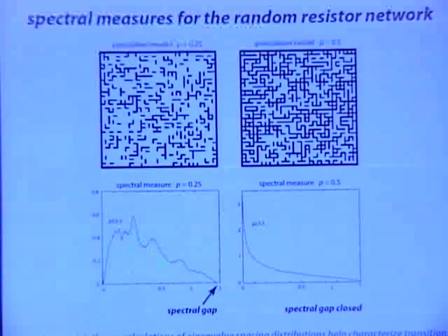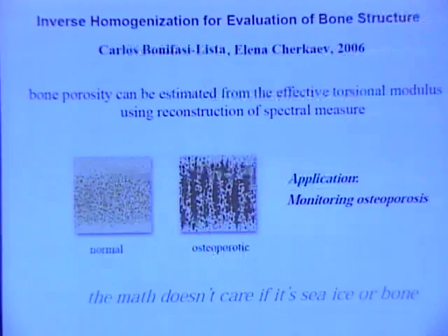The area under this curve here represents the probability, 25%, the probability of finding one of these bonds, and the spectral gap indicates that it's disconnected, and that spectral gap disappears as the system becomes connected. And there's a lot of what's called random matrix theory that underlies some of our analysis here.